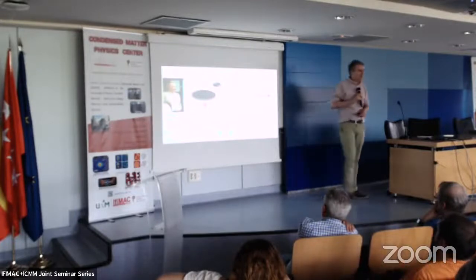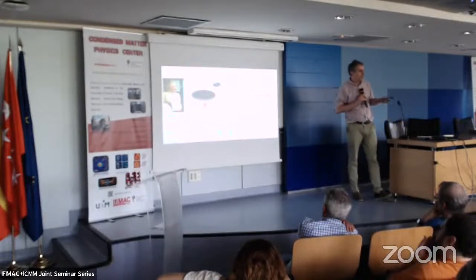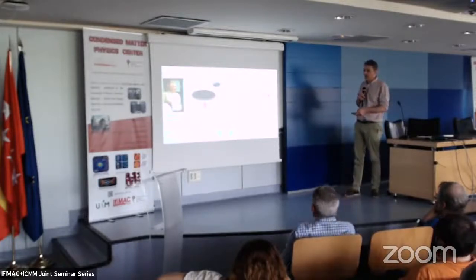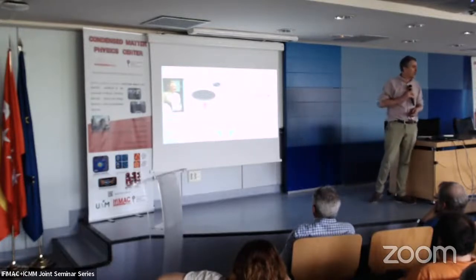Now, when superconductivity was found, one of the first experiments they did was to measure the thermal conductivity. The thermal conductivity of something which has zero entropy, like superconducting electrons, is exactly zero. They managed to make some material where the superconductor is interspersed by normal areas, and there they found that the thermal conductivity is also zero. This was very puzzling.